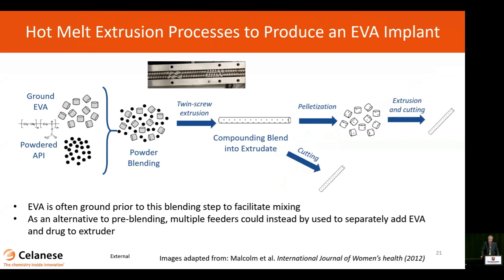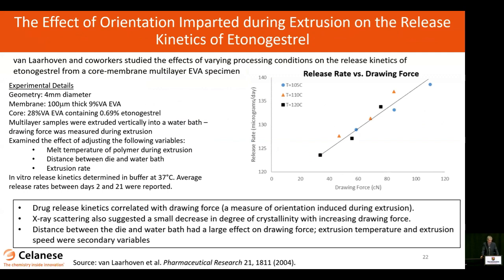Hot melt extrusion. So these implants are typically made through some sort of a hot melt extrusion process where drug is compounded with polymer via a twin screw extrusion. And then there's some subsequent co-extrusion process where you make the final implant. And so if you go to the literature on this, you'll find that there's big dependency. There can be effects of processing conditions on drug release characteristics. And so this is a nice publication from about 20 years ago where they varied a lot of process parameters, and they showed that the release rate from a multi-layer implant was a function of the drawing force that they measured, which is really a measure of the orientation that you're getting in that polymer during the extrusion, drawdown, and cooling process.